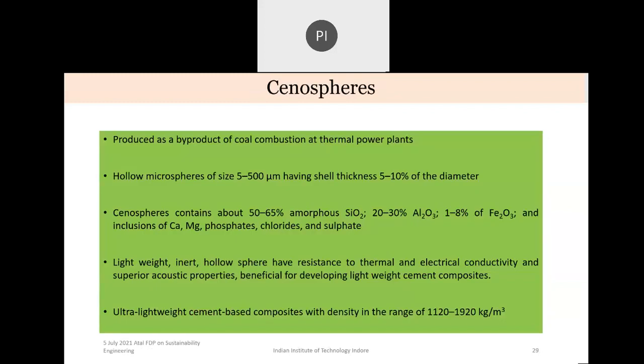Another material is cenosphere. This is produced as a byproduct of coal combustion at thermal power plants. And these are hollow microspheres of size 5 to 500 micrometer, having shell thickness 5 to 10% of the diameter. And they contain about 50 to 60% amorphous silica. And why we are saying again and again amorphous silica is because we know that it's not the total amount of silica, SiO2, that is important. What is important is its presence in amorphous form, only then will it contribute to the reactions.